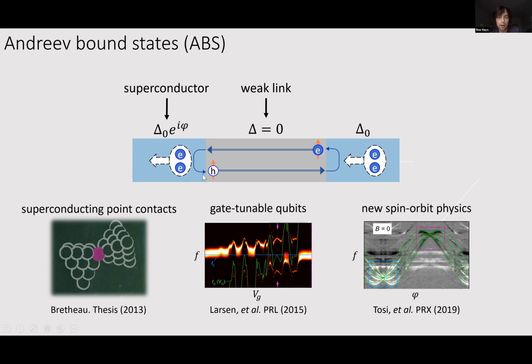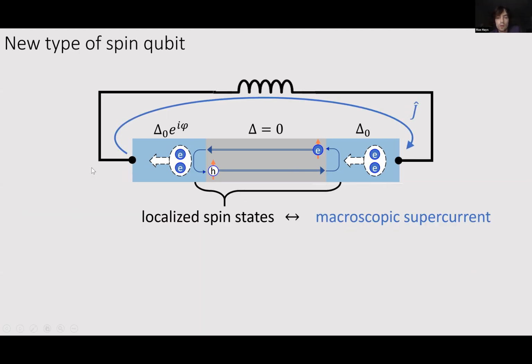In nanowire-based weak links, it's been shown that you can make gate-tunable qubits, and then we also saw in the last talk that we can look at new spin-orbit physics, also in indium arsenide nanowire weak links. One of the reasons we think Andreev bound states are so interesting is that they actually give rise to the current operator of the weak link. And this means that you can couple to them and probe them in ways that aren't possible with states in an electrostatically confined quantum dot, for instance.